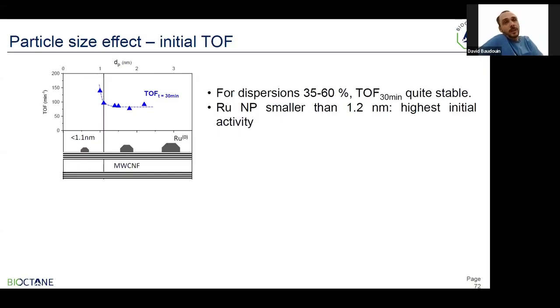So the initial one, at least at the first 30 minutes, as a function of the initial particle size. And you can see that there is no clear particle size effect unless you go to close to 1 nanometer size, where the activity seems to increase dramatically. Next slide, please.